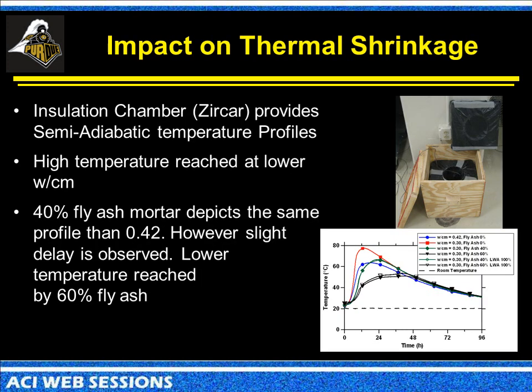Now, in addition to this, one of the other benefits, and this is one of the key issues, I think, the benefit of combining our fly ash with internal curing is we can take advantage of both factors here. By adding water into the system through internal curing, we reduce autogenous shrinkage, but the use of the fly ash helps us to monitor and maintain the temperatures that are developing in those systems at a lower level.